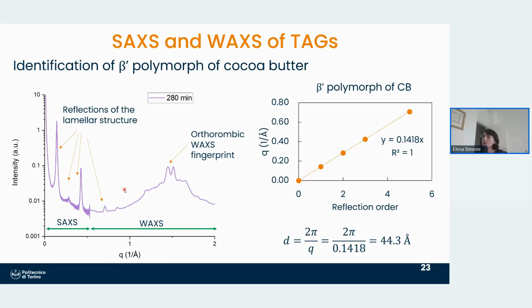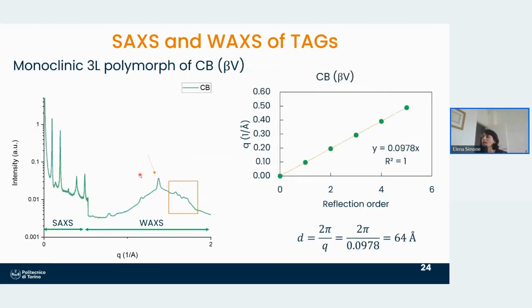Beta prime polymorphs have a very similar kind of SAXS pattern, with a slightly different slope, and the WAXS fingerprint is characteristic of an orthorhombic form. And then a monoclinic form for the beta. The SAXS region can be used, for example, to check how many phases are present in my sample, because I will have as many phases as many lines I can draw.